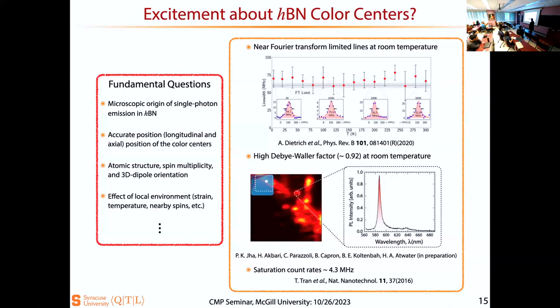That's one. The other open question was, we, like everyone else, work with really thick single crystalline samples, but then where is it located? And I will show you some of the results. Using super resolution microscopy, you can find it very precisely in the XY direction. But if you take a thick sample, let's say 200, 300, 400 nanometers thick, you find where it is in XY, but you don't know where it is located in depth.